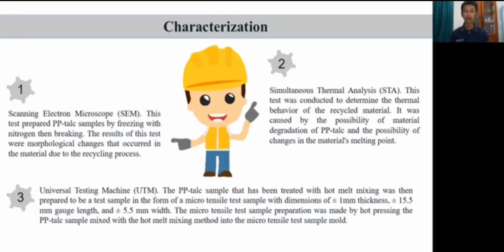The PP talc sample that has been treated with hot melt mixing was then prepared to be a test sample in the form of a microtensile test sample with dimensions of more or less 1 millimeter thickness, 15.5 millimeter gauge length and more or less 5.5 millimeter width. The microtensile test sample preparation was made by hot pressing the PP talc sample mixed with the hot melt mixing method into the microtensile test sample mold.